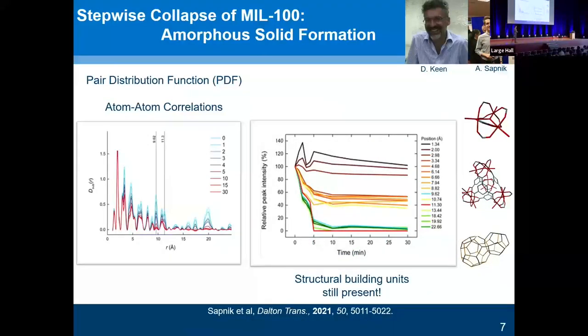Adam then went one step further, trying to think, well, what is that amorphous material? So use pair distribution function work, distance in R, angstroms along the bottom. And then when we see a peak, two atoms connected by the peak. Some beautiful work by Adam integrated each of these peaks over the ball milling time, so over this progressive collapse, and then looked at their intensity. And actually, the intensities fall into three categories.